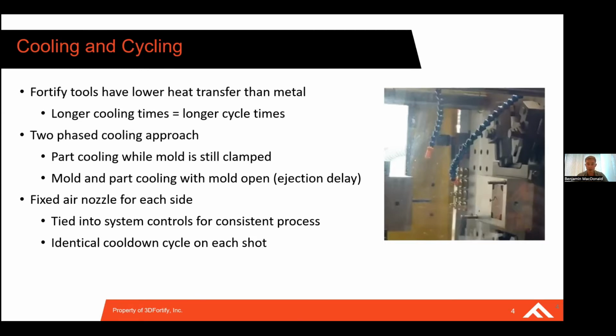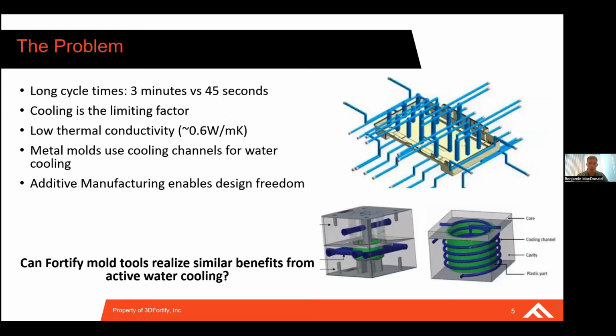The compressed air ends up taking anywhere from 15 to 30 seconds depending on the part size and the temperature of the plastic that we're injecting into the tool. So in total, we're looking at anywhere from 70 to potentially 120 seconds of cooling time that really drives up our cycle times, because that can be upwards of 2 minutes alone just for cooling the part itself. So that's really what our problem is today.